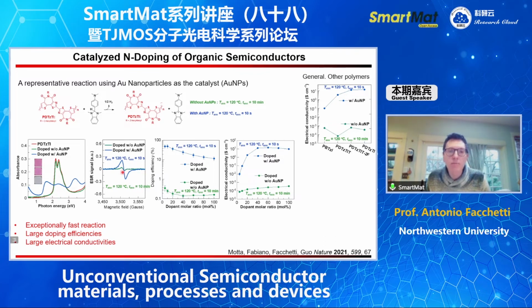This is an EPR. Without catalyst, the spin density is much lower. And this is the electrical conductivity when we compare the process for different molar ratios between the polymer and the dopant. This is not so important. With no catalyst, the doping efficiency is very low. The conductivity is much lower. In the presence of catalyst, with much less time, the doping efficiency is much larger, and the electrical conductivity, when you improve the doping content by about 40%, is much, much larger compared to the uncatalyzed system.